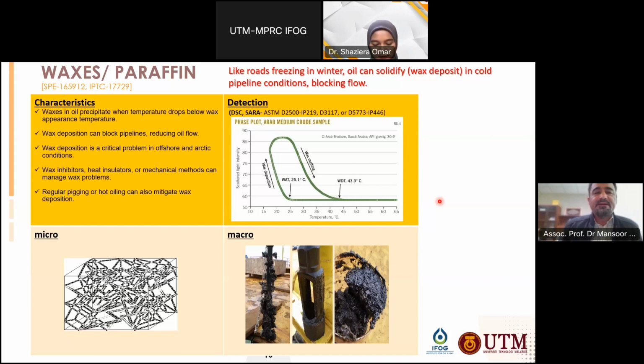And of course, there are standards and ways of detecting this. WAT stands for wax appearance temperature, and also wax disappearance temperature is very important here. These are 2 important parameters when we are dealing with wax in crude oil. The temperature at which wax begins to crystallize and precipitate out of the solution is WAT. As the temperature of the oil drops below this point, usually when being transported from the hot subsurface condition to the cooler surface or subsea, the wax begins to solidify and can start causing issues